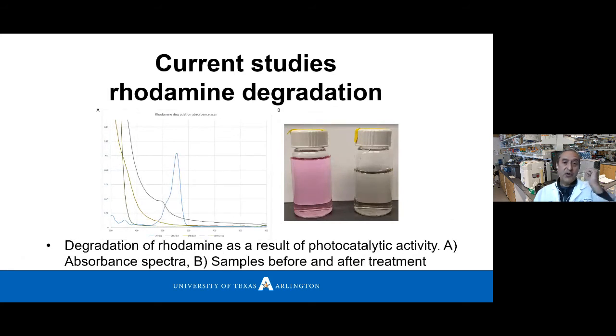And then we used rhodamine to test the formation of free oxygen, or reactive oxygen species. In this case, we expose rhodamine, which can decompose under the action of oxygen, as a way to check if our material was generating these oxygen species. On your left, on graph A, you can see a peak. That peak is when rhodamine is in initial conditions. And then you can see how the peak reduces until it totally disappears. And on the picture on your right, letter B, you can see the material before the treatment in the pink color and after the treatment when it becomes totally clear. That's evidence that the action of the nanoparticles was effective at decomposing the rhodamine.